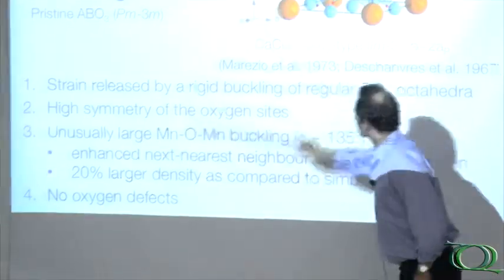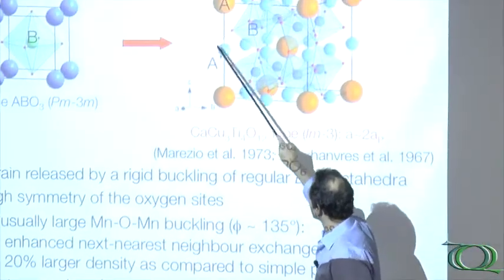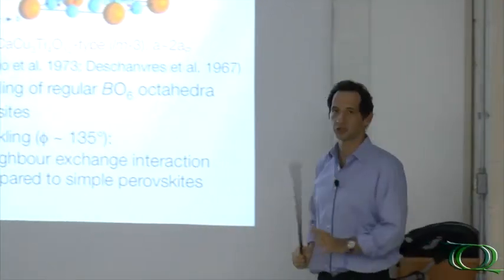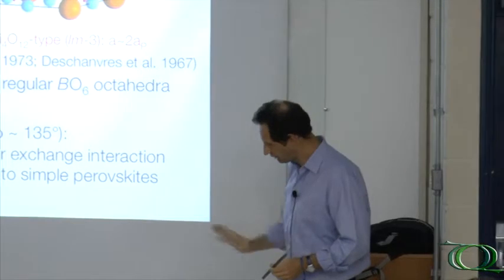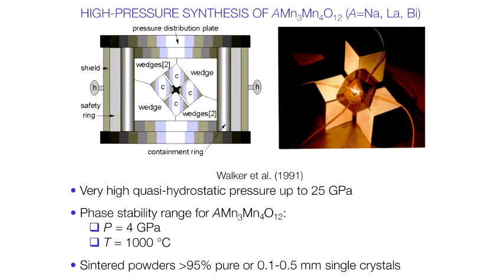I will not go into the details, but because of the lower coordination number of this site, you cannot take out oxygens from this structure. So this oxygen structure is disorder-free. No disorder and reduced distortions. We have to synthesize under high pressure. The title here is High Pressure Synthesis.